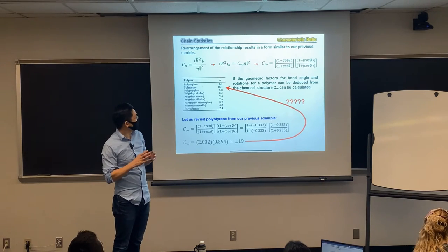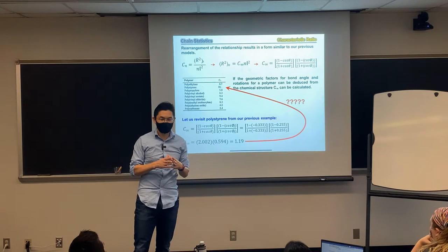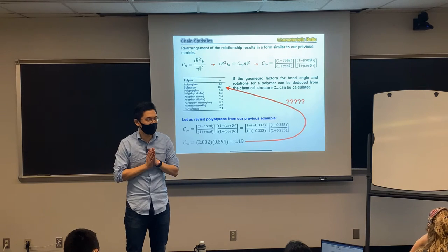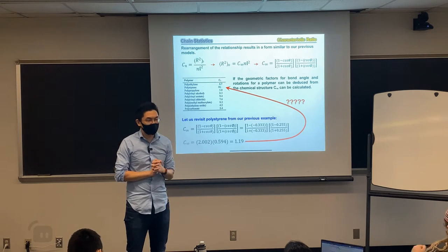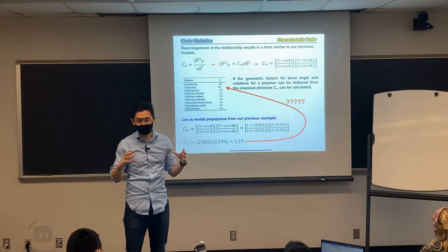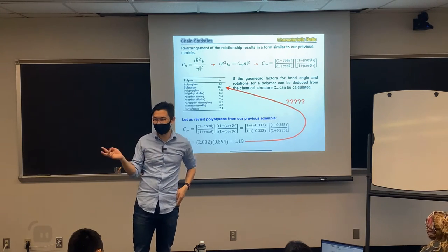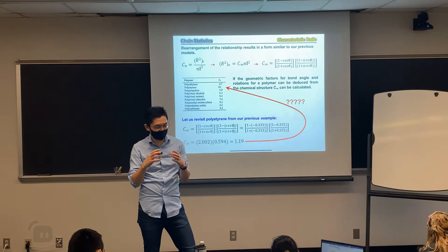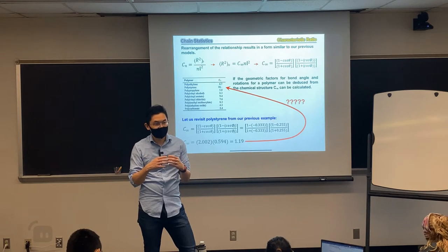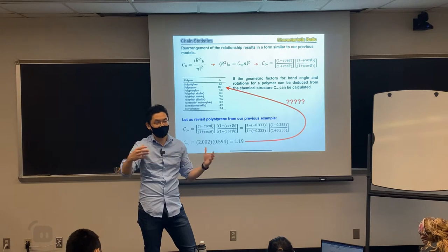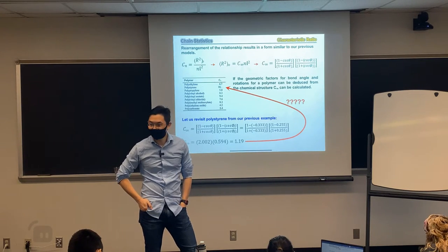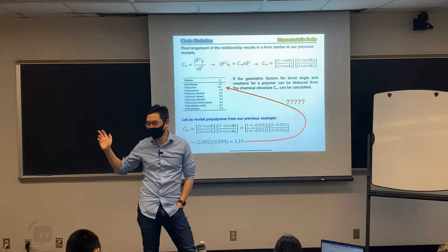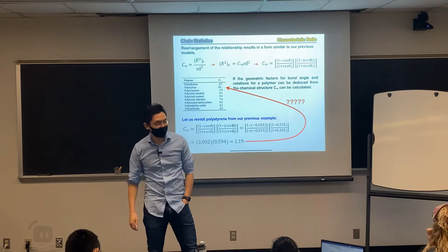This tells you how different the geometry and rigidity of your polymers are. In the next class, we're going to discuss even more detail. C infinity is also proportional to the chain rigidity, expansion ratio. Okay, those three are interchangeable. Expansion ratio comes from the bond angle, etc. This results in the bigger the C infinity, the more rigid the polymer coil backbones are, and the bigger they expand. And we will discuss another term people use when talking about chain rigidity, called persistence length, fairly soon.